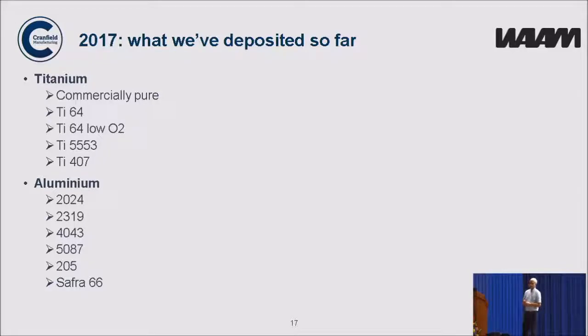So, for example, the 2024, if you want to get that in high performance, you need to do a solution treatment and artificial aging after you've deposited the material. And this is very difficult actually, because you've now got to treat a whole part, and there are going to be lots of issues around quench cracking and distortion, as well as getting uniform quench rates.